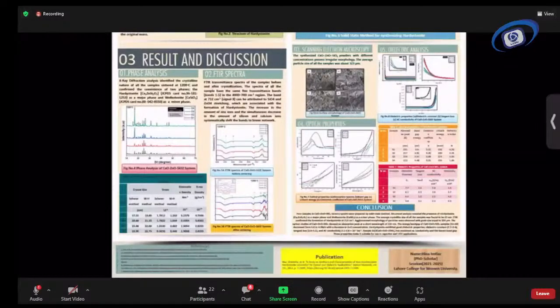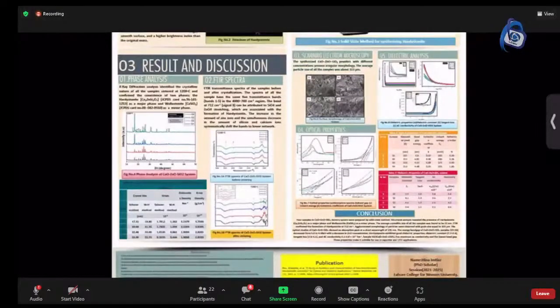So the next technique is dielectric analysis. In dielectric analysis, we have created three types of calculation for the dielectric properties: dielectric constant, tangent loss, and AC conductivity of the system. So by the dielectric constant and the tangent loss, we have comparative results. As you can see, dielectric constant and tangent loss are inverse to each other, which shows that sample 3 has a maximum dielectric constant and AC conductivity and minimum dielectric loss. So we can say that we can use this material in bolometers and capacitors and for LTCC application.